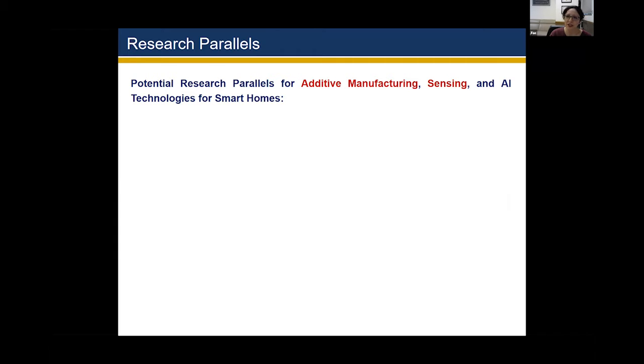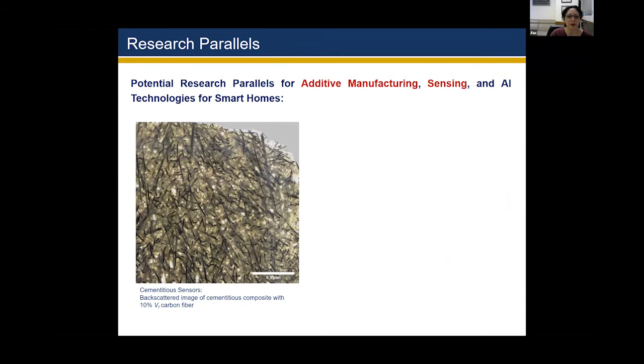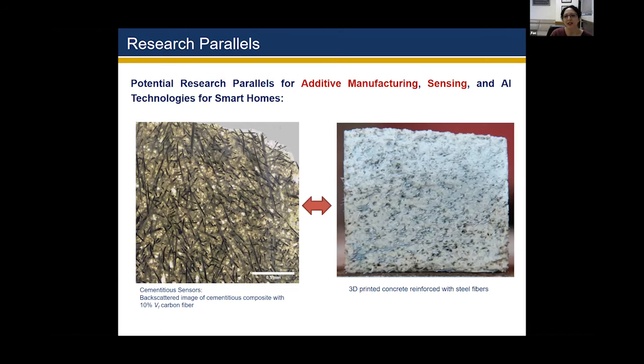Another parallel that I can see, especially in sensing, is that a lot of people have tried using fibers, and specifically steel fibers, to strengthen the bond strength of the 3D printed concrete. And if you remember our cementitious sensors, where we use cement plus carbon fiber, this is just a microscopic image of it. And on the right, you can see an image of a 3D printed piece of concrete that has steel fibers in there. So I imagine that because steel fibers are conductive, that material could potentially also be a 3D printed cementitious sensor.